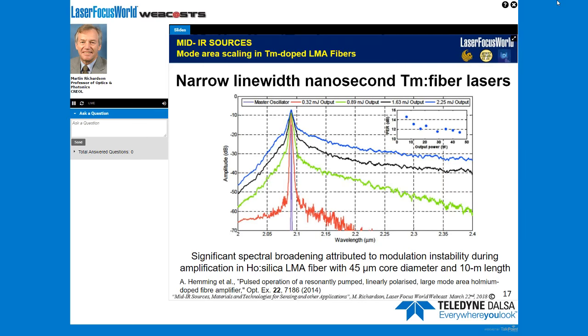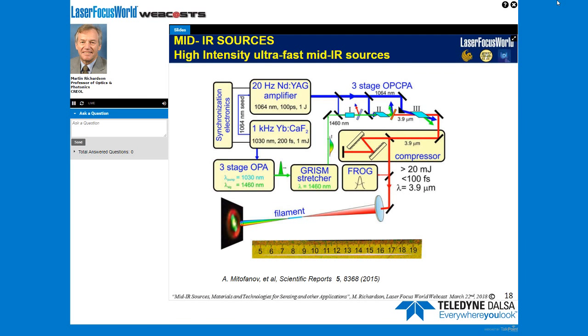Fiber lasers are not the only source of high powers, particularly with ultra-short pulses. There are a number of research groups now that are working on high-intensity ultra-fast systems. Much of the effort started off with Ti sapphire lasers in the last century and is still continuing now. But now using optical parametric CPA approaches, and in some cases new crystals, we're able to generate by OPCPA ultra short pulses at wavelengths beyond 4 microns. In fact, up to 6 microns has now been demonstrated at relatively high powers.